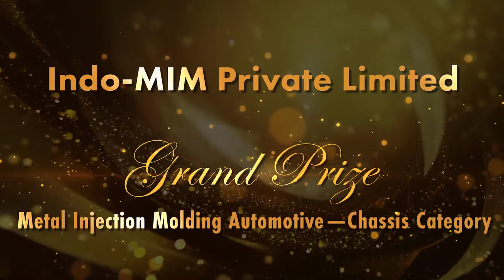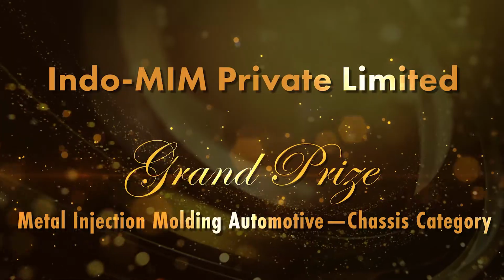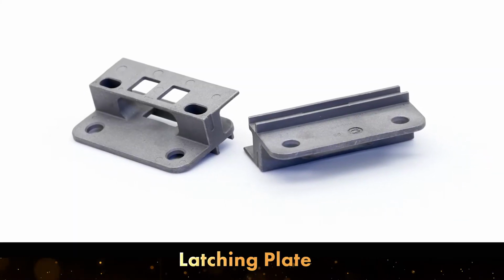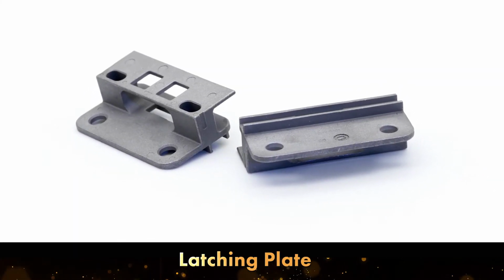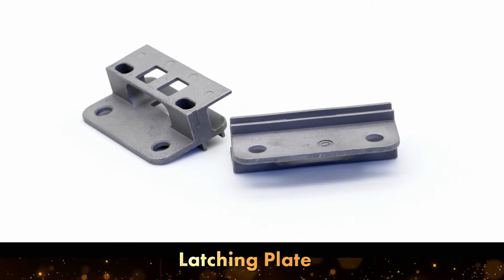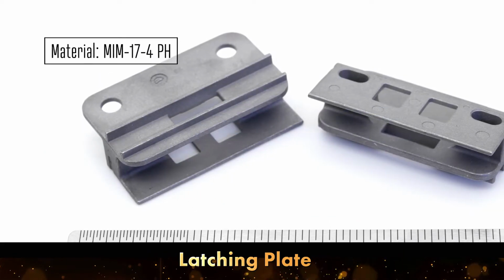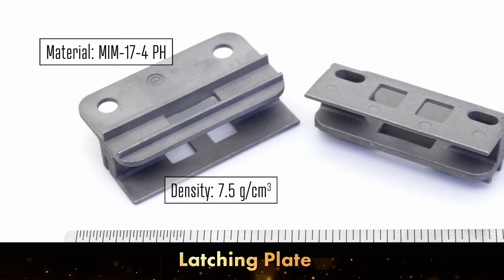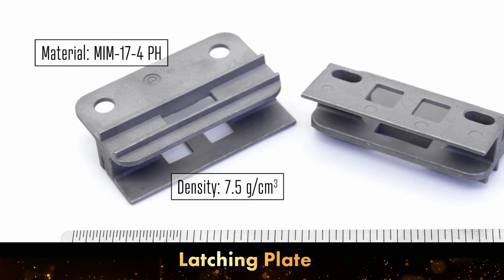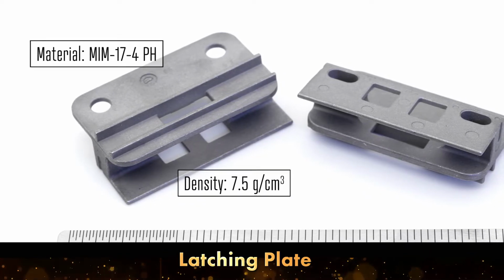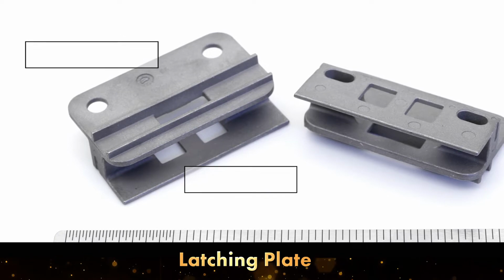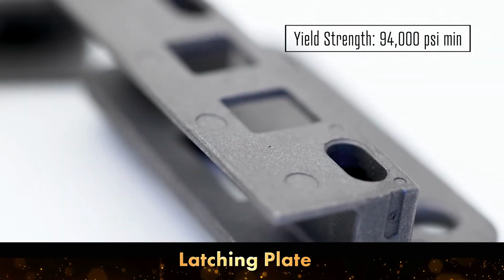Indo-MIM Private Limited has won a grand prize in the automotive chassis category for MIM components. This award-winning component is a latching plate used in a collapsible roof assembly for passenger cars. The part is made from MIM 17-4 PH in the as-sintered condition and has a typical density of 7.5 grams per cubic centimeter, with a minimum yield strength of 94,000 psi.